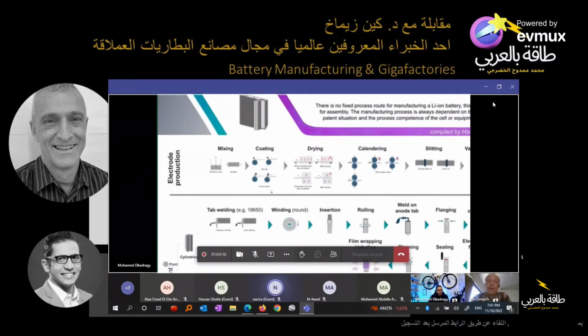Why two different glues? Well, it turns out that one of them, the CMC, is good at cohesion, which is gluing the graphite to the graphite. And the SBR, the styrene butadiene, is good at adhesion, gluing that whole thing to the foil, the anode to the copper foil. But there are other binders and other binder combinations you can use. Now remember, you want to use as little binder as possible, because the only thing binder does is glue things together and take up space that doesn't help a battery be a battery. So you try and minimize that.